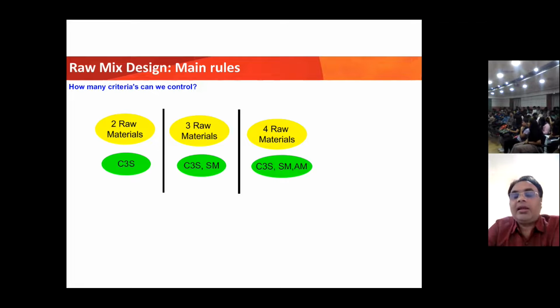All are governed by three governing factors, from the raw material to the finished product, that is LSF, SM, and AM. LSF is the lime saturation factor, and it has a formula I will show you. And silica modulus is there, and AM is the alumina modulus. So all these governing factors are there. And finally, inside the kiln, your clinker is formed at a temperature of 1400 degrees Celsius, right?